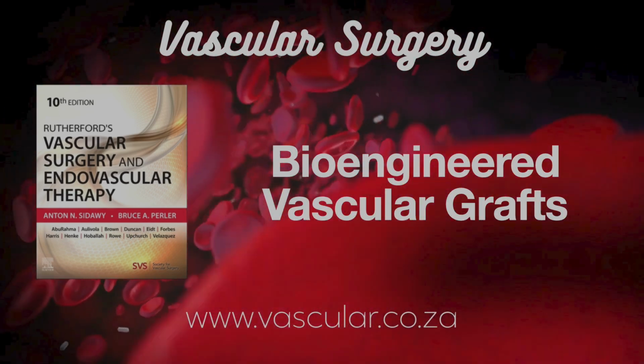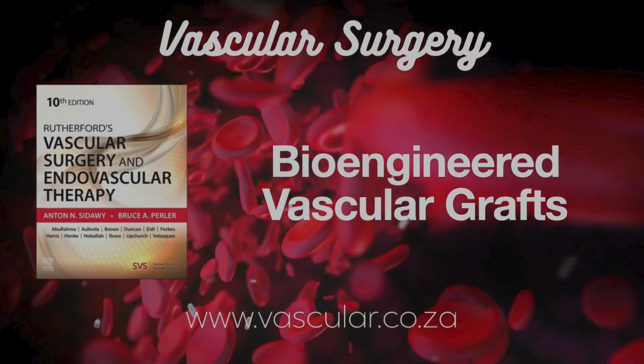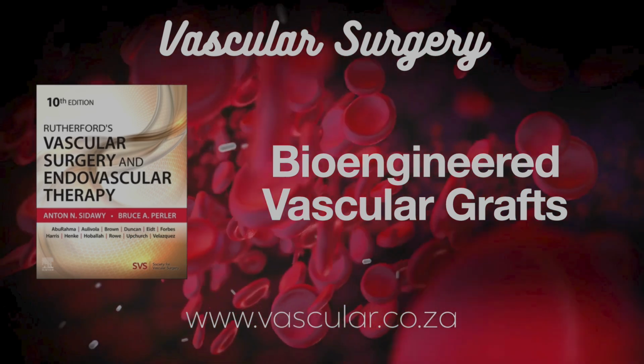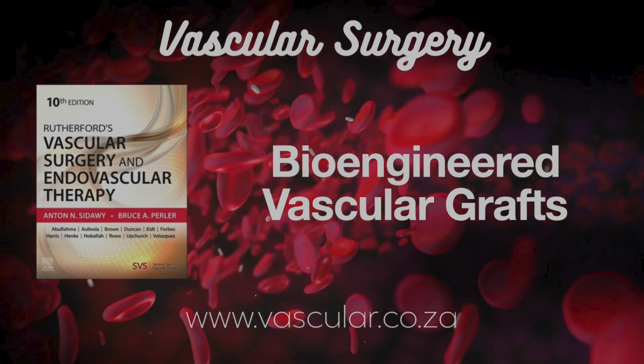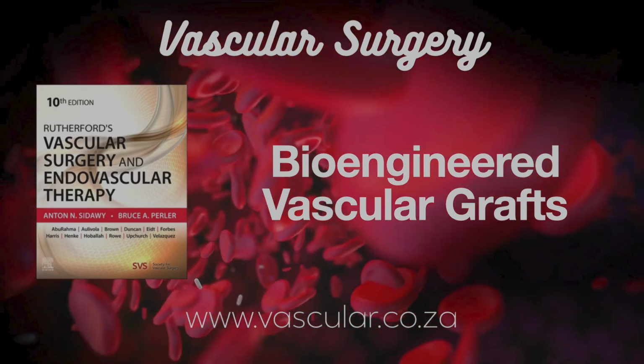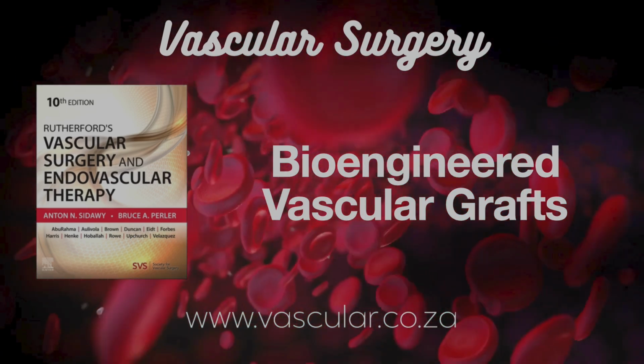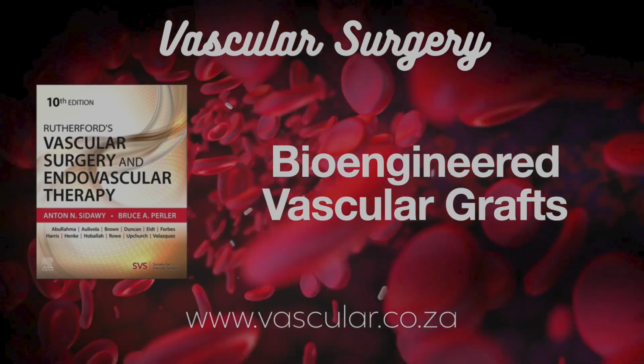Early attempts struggled with structural integrity. But Nicolas L'Heureux and his group developed a pretty sophisticated process, using cells from human umbilical cords, smooth muscle cells and fibroblasts for the wall, and endothelial cells for the lining. They managed to create a completely biological human vessel this way that was strong enough. Any downsides? The main one was time. It took like 4 to 6 months to manufacture one vessel. Very labor-intensive. And this led to a clinical product, Cytograft's Lifeline.